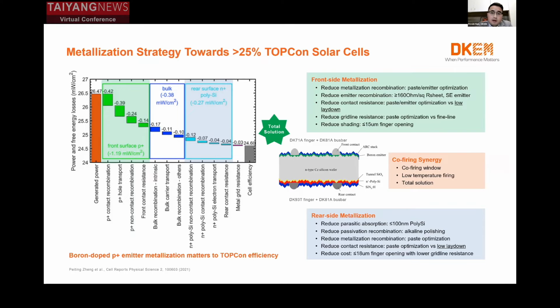So we have to put a lot of effort into this part, and we always observe the trend that lower and lower laydown requires lower and lower resistance. This is a challenge. We still need to reduce the grid line resistance. Also, for front side metallization, reduced shading is always the theme for us. How to modify the paste to enable a finger opening of less than 15 microns is also an action item for us. The second category is the rear side.